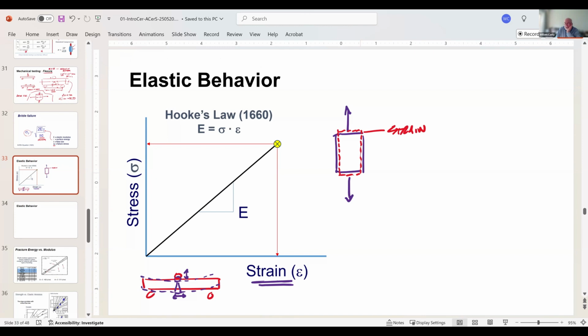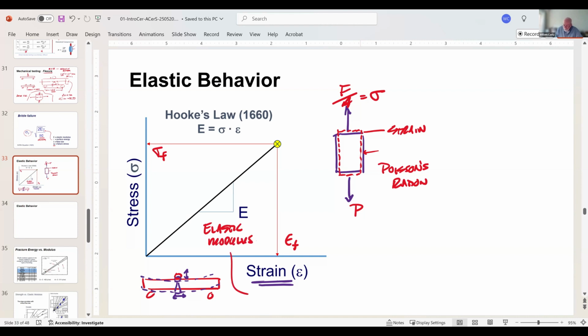The amount of force I have to put on here, force divided by area, is my stress. So if I pull on this with a load called P, my sample elongates and contracts in the middle. That gives me what's called a Poisson's ratio, the ratio of how much it contracts to how much it elongates. In a perfectly brittle material, my stress goes linearly with strain until I get to a strain limit, the strain at failure, and I get a stress at failure. The slope of this line is the elastic modulus. It's also sometimes called Young's modulus, after a guy named Young.